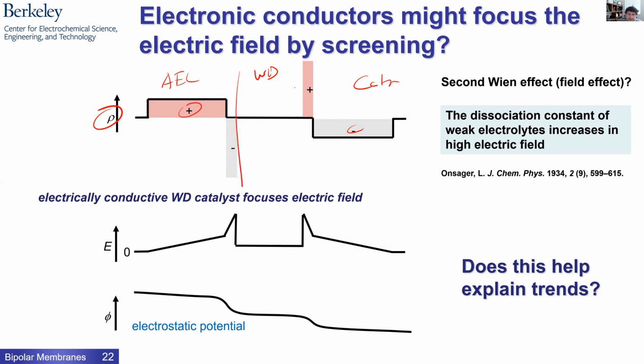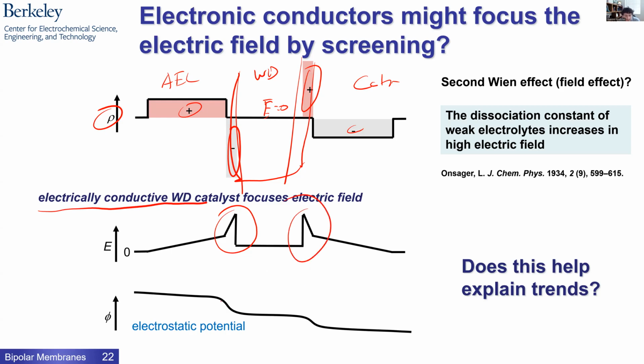Now imagine I put a water dissociation catalyst in here that's a really good electronic conductor. Well, those electrons will polarize, right? They'll polarize and all the charge will sit at their surfaces, and the field in the middle will be zero if I just put a sheet of, say, steel in the middle there. It would screen that electric field completely. So you could think about electroconductive water dissociation catalysts somehow focusing the electric field, focusing where the potential drops, by a redistribution of free electrons or any electronic ability to strongly polarize in the presence of this field. So we thought maybe this is an explanation.